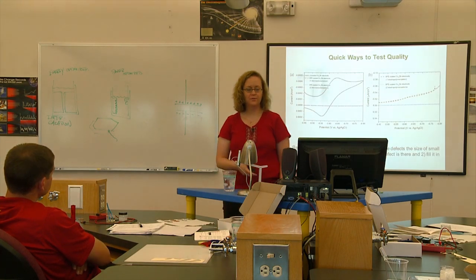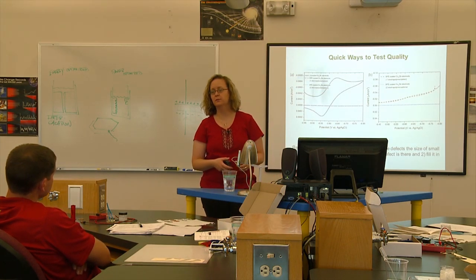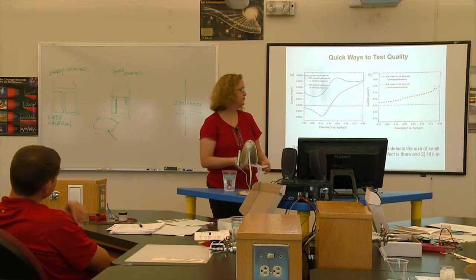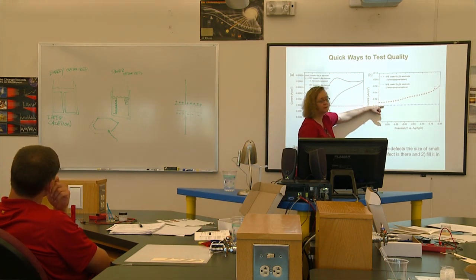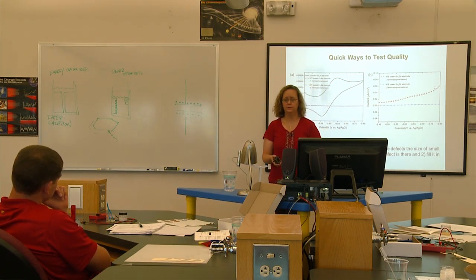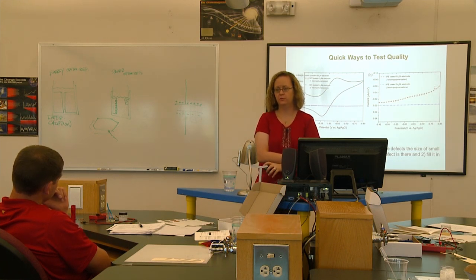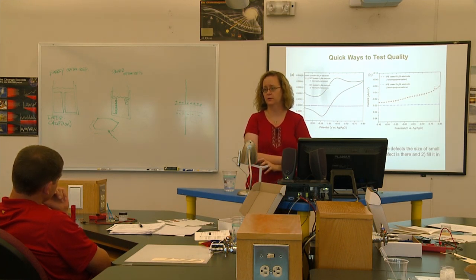So now that we've optimized our polymer deposition, the guys are at about one out of every 45 has a defect. And if they see this flat line, when they put the full battery together, out of batches of 50, we're at 50 out of 50 that don't short. That doesn't mean they work great for other reasons, but it means they don't short. So now it actually works. This idea actually works.